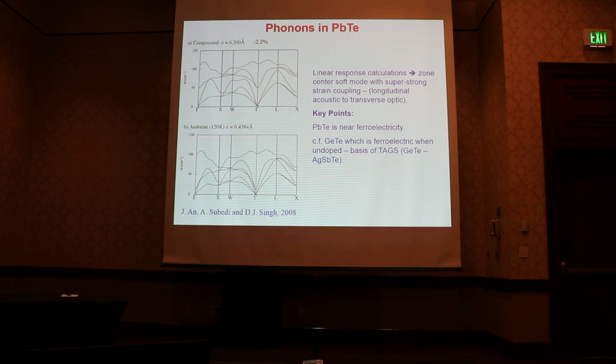It's quite delicate as far as methods go, but this really is the low temperature energy of the polar transverse optic mode in lead telluride. And then, as is not surprising to people in this audience, I also learned about this at the Williamsburg workshop. There's a strong pressure dependence of ferroelectric modes in many materials, and lead telluride is no exception, although that wasn't previously studied.